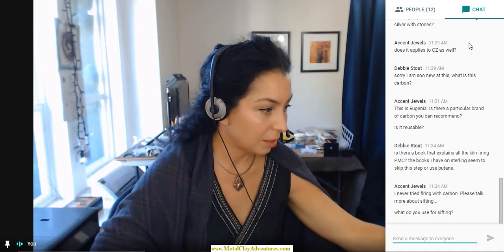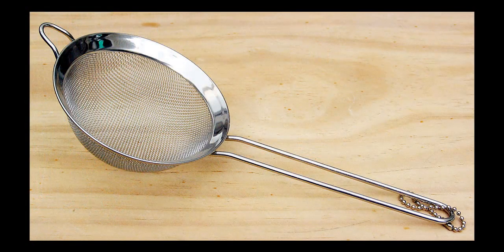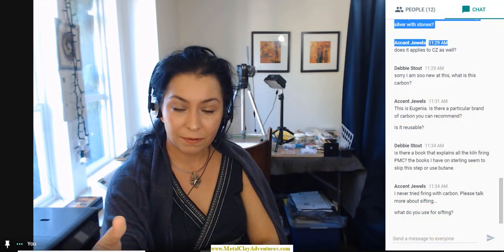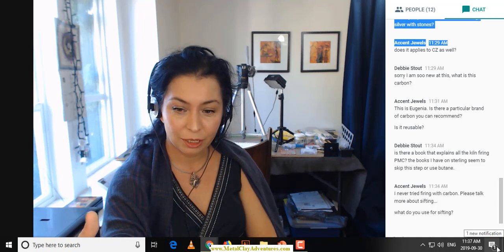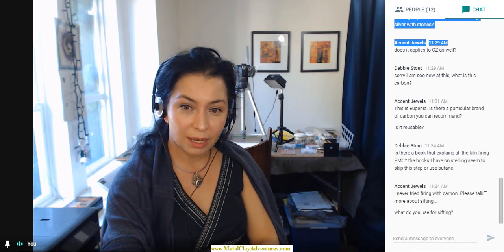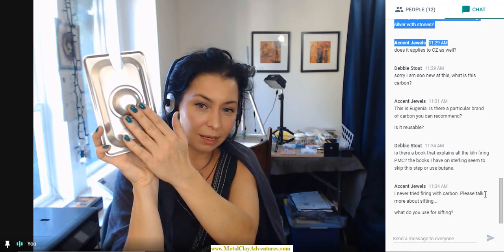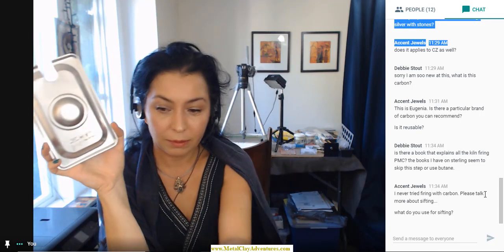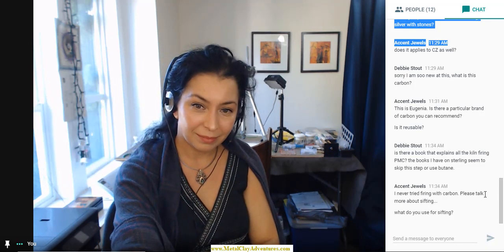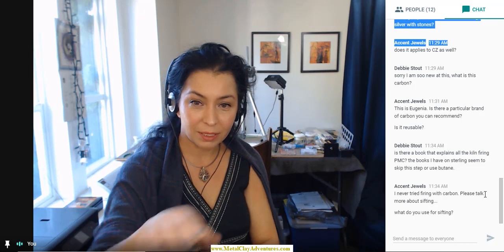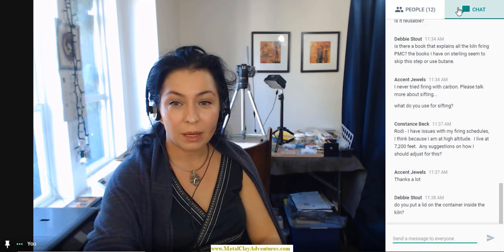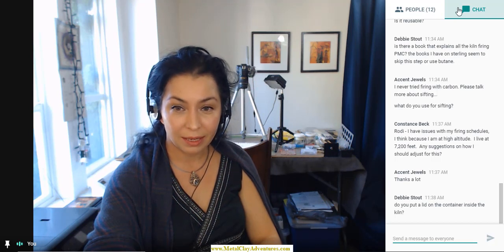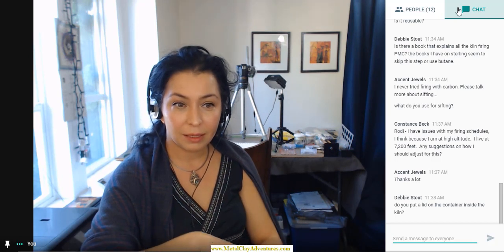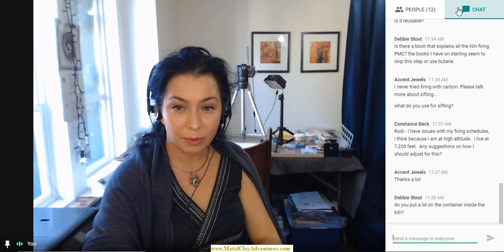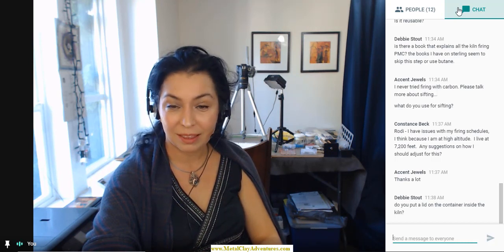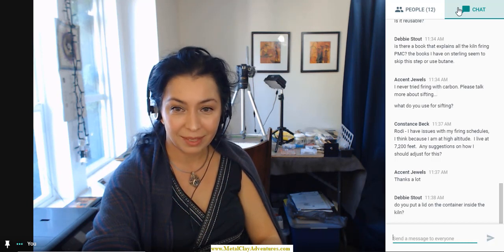So why are we doing this? Because the carbon will take fire and form the muffle, but the ashes will not. Another thing is that you'll have ashes from the lid and from the container itself, which can deform your piece. So we need to clean it every time after firing. Anyway, we are aiming for the best we can get from metal clay. But we need to remember that our metal will be more porous than the metal which is formed under high pressure.